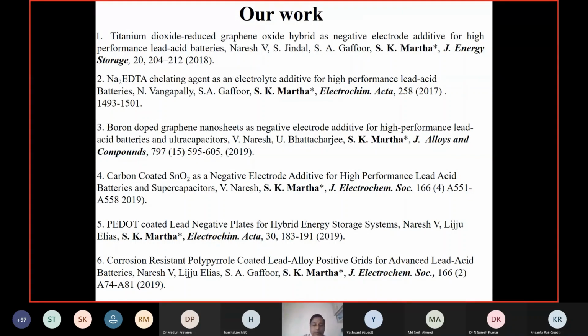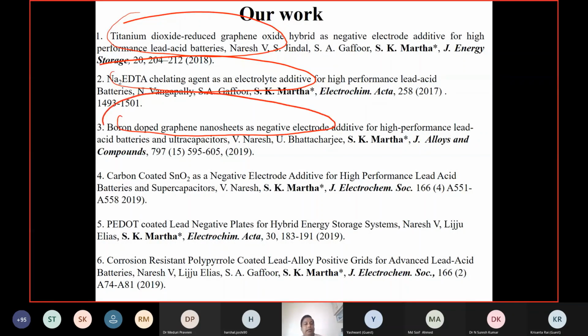We have developed, one of our students, Dr. Naresh, worked on this and developed titanium dioxide graphene oxide as an additive for the lead acid battery. Also, he developed some electrolyte additives. Boron-doped graphene nanosheets are a negative electrode additive to lead acid batteries. Carbon-coated SnO2 as a negative electrode additive. Why with the metal oxides? Carbon improves the conductivity, but what happens at high voltages? There will be a possibility of carbon dioxide evolution.